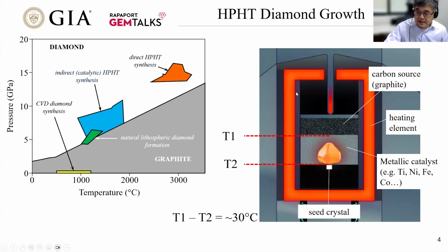On the right-hand side is a diagram showing the assembly, the cell, how an HPHT diamond is actually produced. To grow diamond, obviously, we need carbon. So in this diagram, the middle part, the black area, is the carbon. Obviously, this assembly is under high pressure and electricity runs through this heater. The red area is a heater to make the center material reach a very high pressure and temperature. At that condition, the graphite here is going to dissolve into this metal. The metal at this temperature will be liquid. Carbon dissolves easily into this liquid metal, which we call the catalyst.